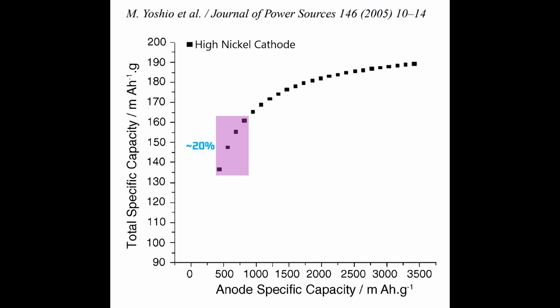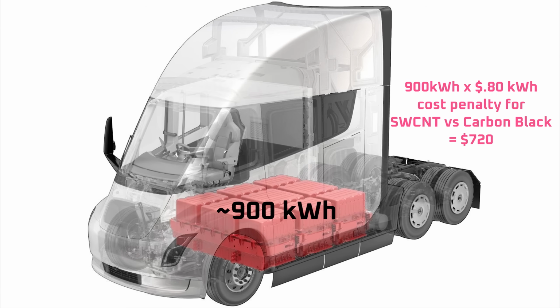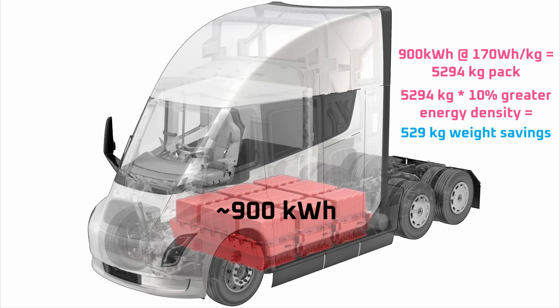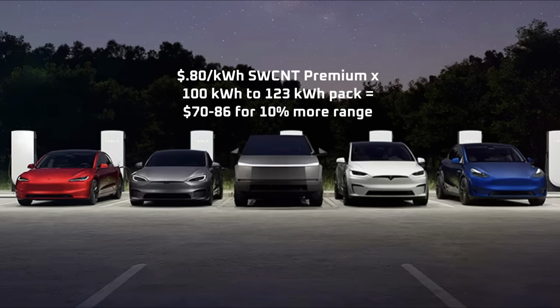In fact, if single-wall carbon nanotubes enable high-energy density silicon anodes, the reduced battery pack weight could actually end up saving money. For example, if the battery pack in the Tesla Semi is 900 kilowatt hours, carbon nanotubes would add about $720 to the cost of the pack. That would cut 529 kilograms of mass from the battery pack. That means over the 1 million or so mile life of the Semi, half a ton of additional cargo could be carried on each trip, or half a ton less mass being dragged around that causes wear and tear on the tires and powertrain. In the case of Tesla's premium vehicle trims, like the Model S or Cybertruck, it could allow, for example, 10% more range at a cost of $70 to $86 on a 100 to 123 kilowatt-hour battery pack.